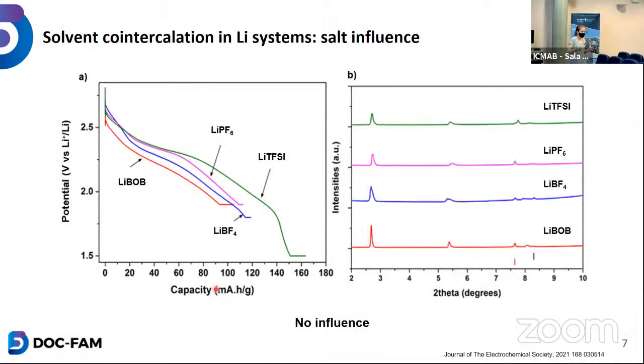So to understand what the triggering factor of the co-intercalation is, we tested different electrolytes with different salts and different solvents. Here we fixed the solvent composition. It was EC/PC, ethylene carbonate and propylene carbonate in a 50-50 ratio, and we used different salts. So as you can see, the capacity is not very impacted, neither is the X-ray diffraction pattern. So we concluded that the salt had no influence.